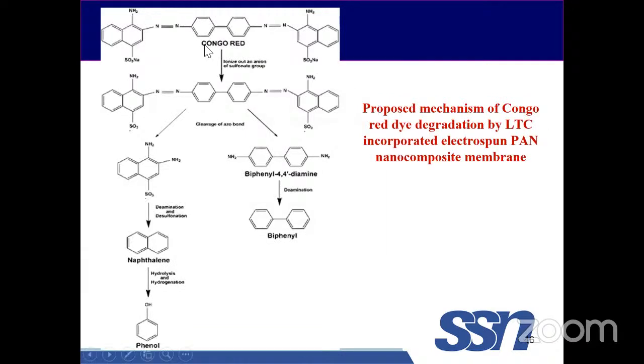Like the Congo Red is being cleaved. We get a cleaved azo dye. Right? These cleaved biphenyl diamine, on deamination, gives biphenyl, and this amine group, on deamination and desulfonation, gives naphthalene, which again undergoes hydrolysis and hydrogenation to give phenol. That is why we got biphenyl, naphthalene, and phenol as the byproducts in this case.